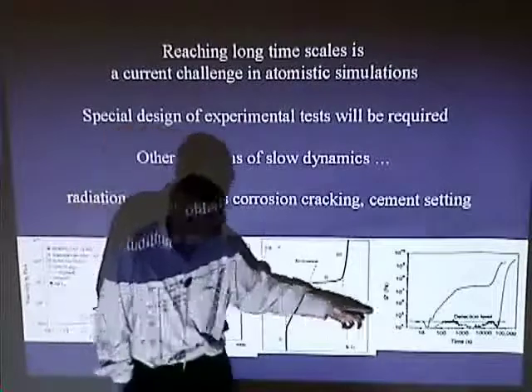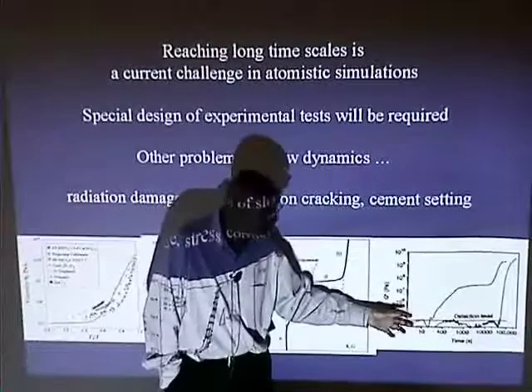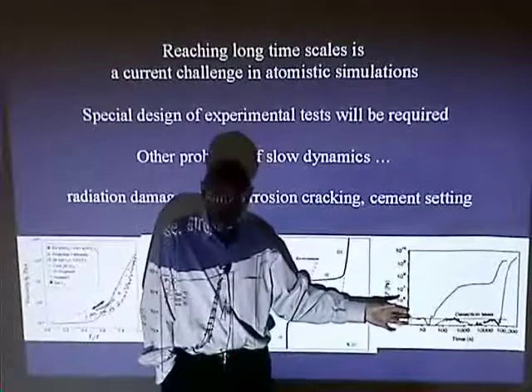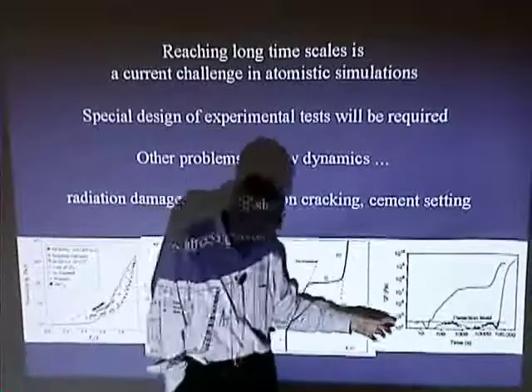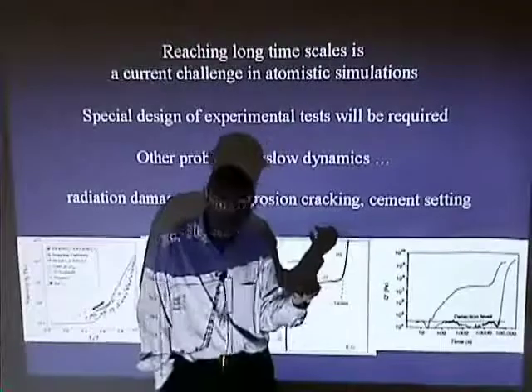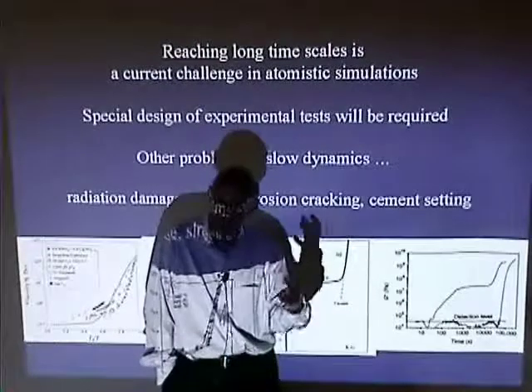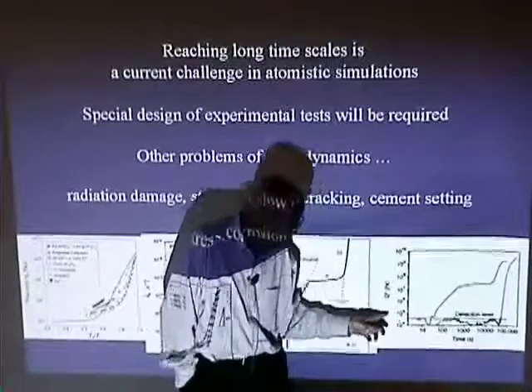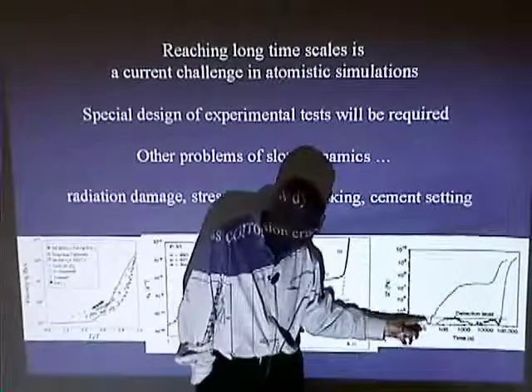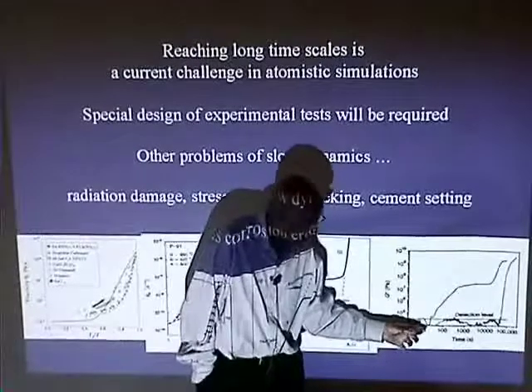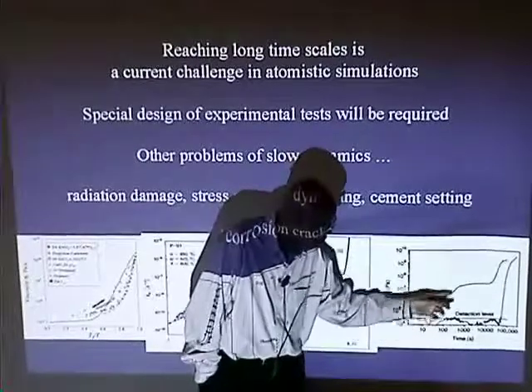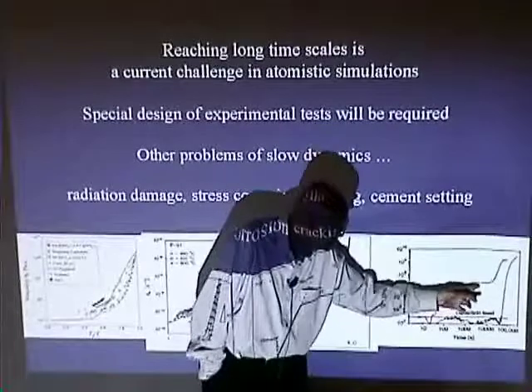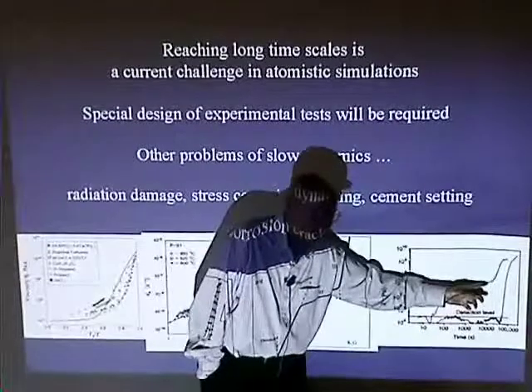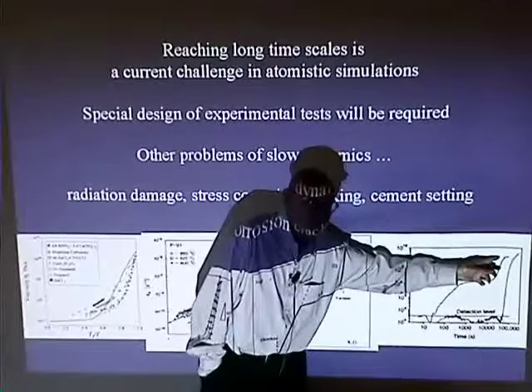The ultimate thing is that this is the curve for cement. In cement, everybody knows this curve, but nobody can really explain it. That is why if you mix cement powder with water, you get a slurry; you just sit there, and as a function of time, the shear modulus goes from zero, basically no shear modulus, up to some sort of coagulation period, then plateau, and then sits there. Come back the next day, it rises too.